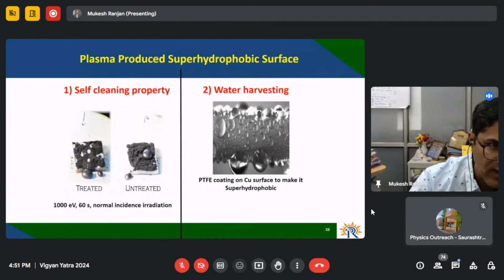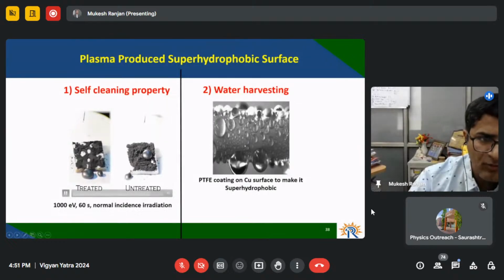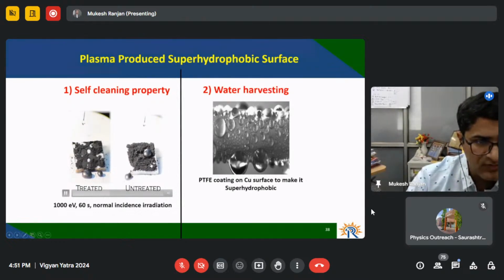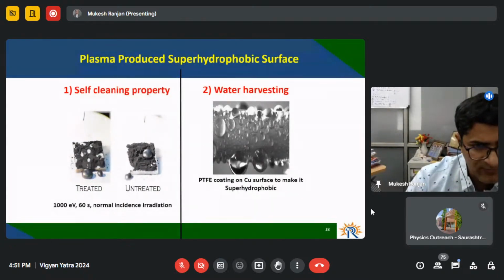the water droplet. But in the second case, you can see that the droplet is going over the surface, but it is not actually taking away the dust. So that's how this technology can be used for self-cleaning processes.